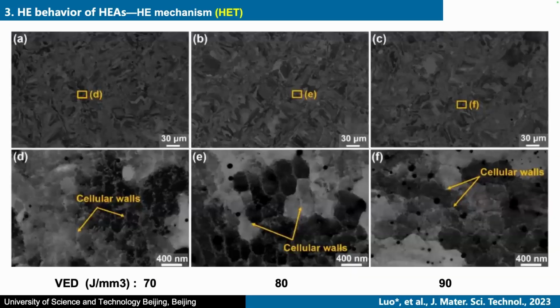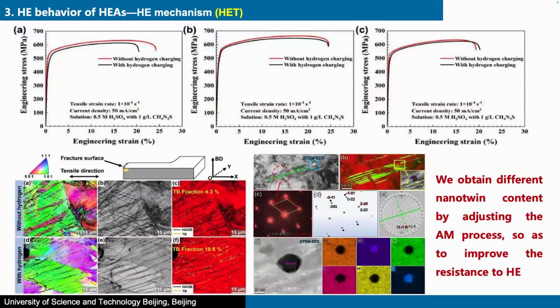So to confirm our results, we did another experiment. We use different additive manufacturing processes to introduce different types of nanotwins. And we found that if we control the density of nanotwins, we can get different hydrogen resistance of this type of alloys. You see, this is hydrogen sensitive. This is also very good. So we think hydrogen enhanced nanotwin is very important in high entropy alloys.